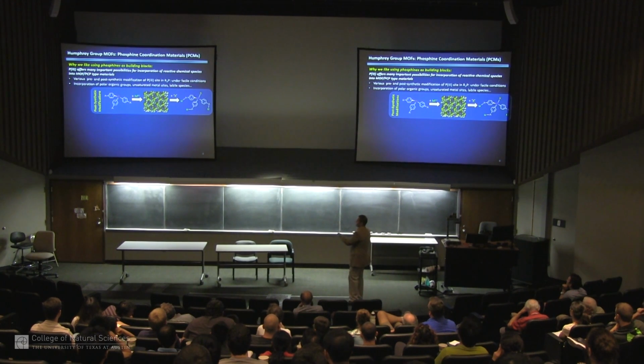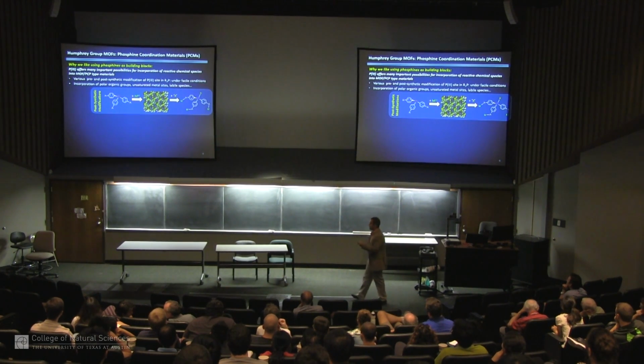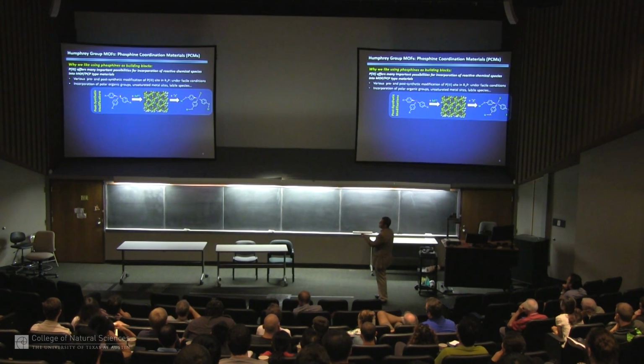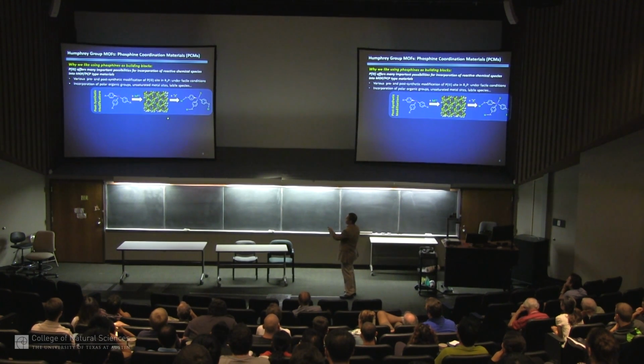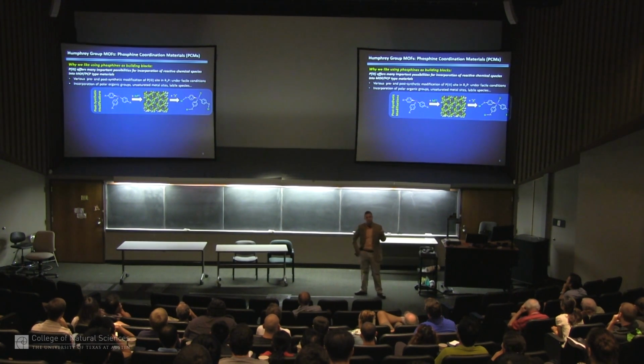And so we're making things that look, to all intents and purposes, like triaryl phosphines, but they have ancillary acid groups that we put in particular positions that allow us to react with a metal that's hard enough to only react with these acids, and will leave the phosphine alone. So now we make a polymer that's crystalline. We can analyze by X-ray diffraction, and you can see inside the pores we have free phosphine sites. So what we've done is made an ordered 3D polymer of a phosphine ligand.